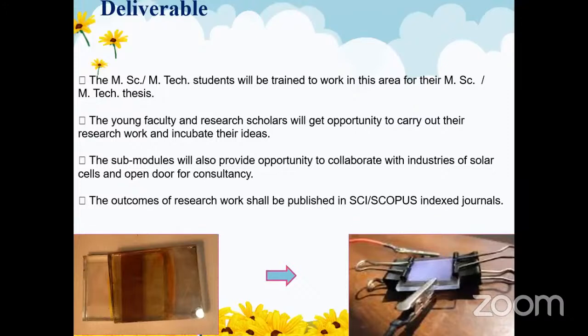Just cut two small pieces of FTO glass. For the working electrode, you put a layer of any wide band semiconducting porous nanomaterial. People generally use TiO2. Some people also use zinc oxide. Then you sinter it at 500 degrees centigrade for 30 minutes, and then put the whole thing in dye solution. Just wait one day, take it out, and then it is a dye coated working electrode.